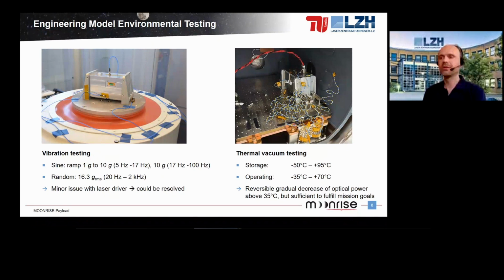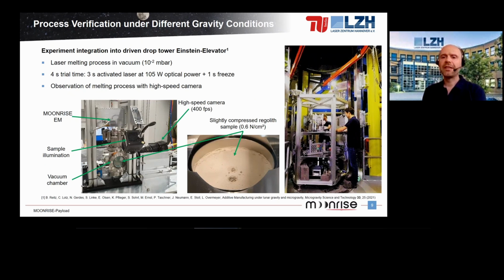There was a minor issue with the laser driver, but it could be resolved, and also thermal vacuum testing. There was a reversible gradual decrease of optical power above 35 centigrade, but it was still sufficient to fulfill the mission goal. Then we went further to verify the process under different gravity conditions.